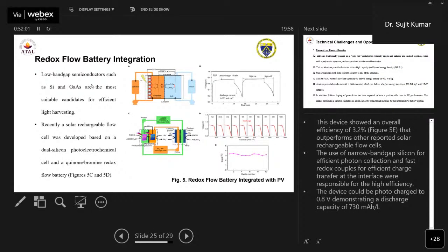Low band gap semiconductors such as silicon and gallium arsenide are the most suitable candidates for efficient light harvesting, since a solar rechargeable flow battery was recently developed based on dual silicon photoelectrochemical cells, based on quinone bromine redox flow batteries. You can see the C section and the D section, which show the charging and discharging of this redox couple battery. This device, the photoelectrochemical cell with quinone bromine redox couples, has shown an overall efficiency of around 3.2 percent, as you can see from this figure, that outperforms other reported solar rechargeable flow cells.